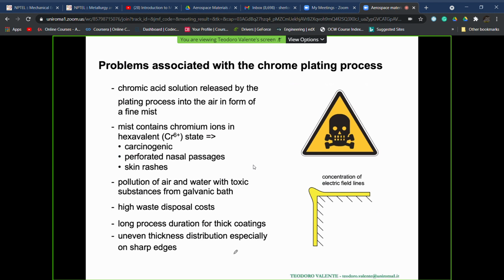But which is the problem of this very cheap, very simple, highly effective technology? The problem lies here in the use of hexavalent chromium inside the bath, in the electrolytic process. And you see here which are the problems for the safety, for the health, I would say, of the operators, which this hexavalent chromium can cause. And this is already known, a well-known state-of-the-art, let me say, effects. And so the need to develop or to use coatings which are different from the hard chromium technology based on hexavalent chromium has started.